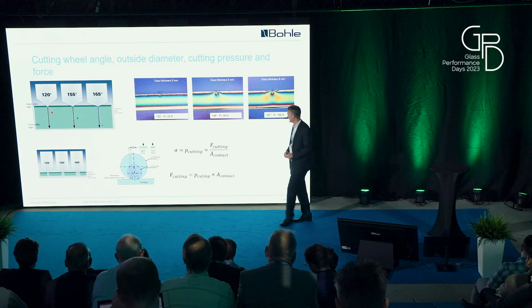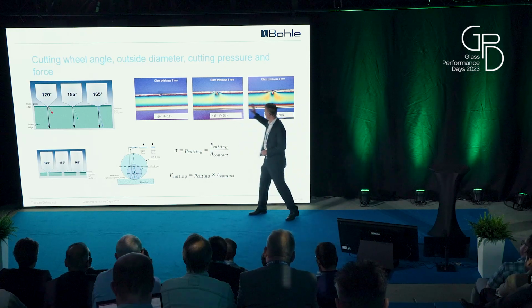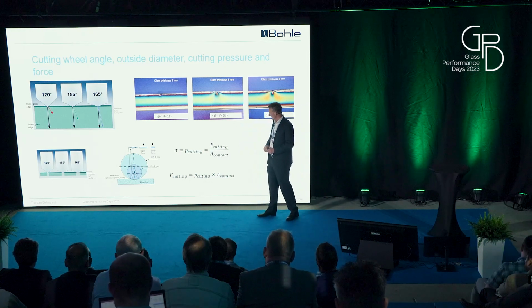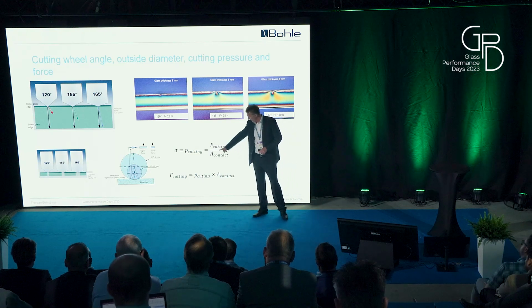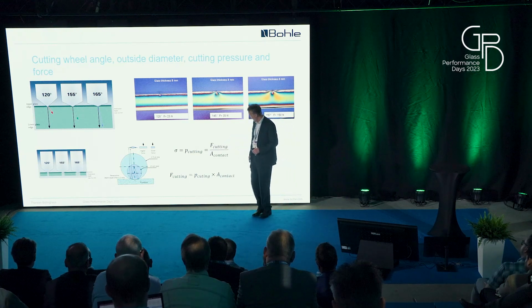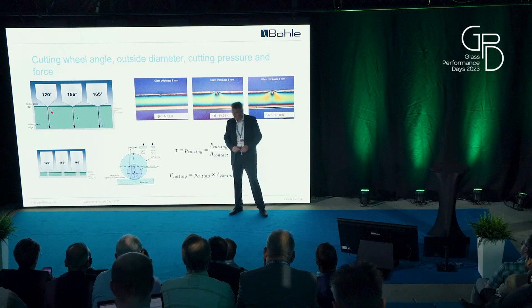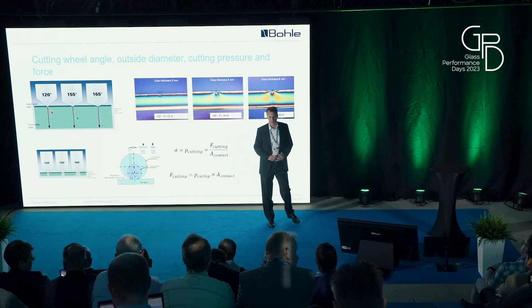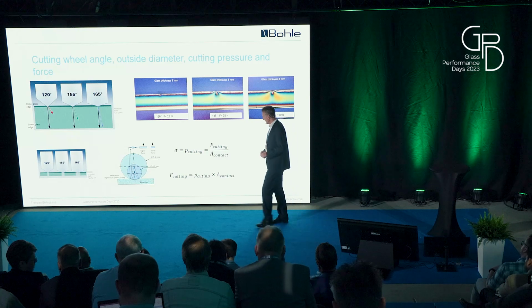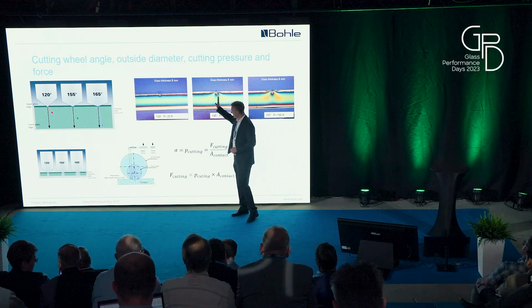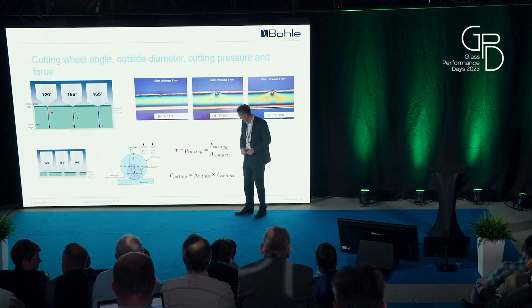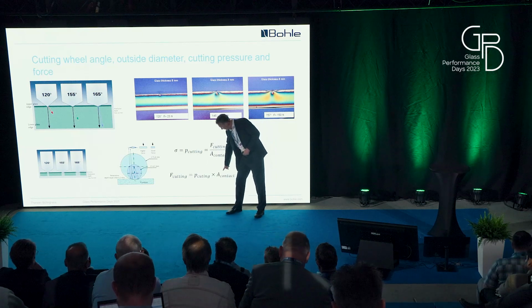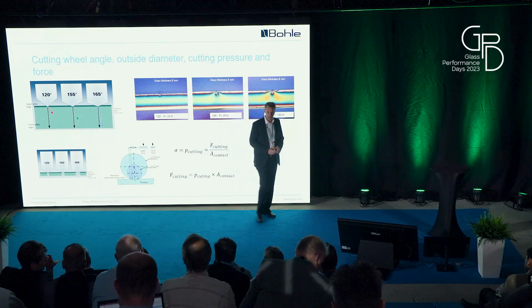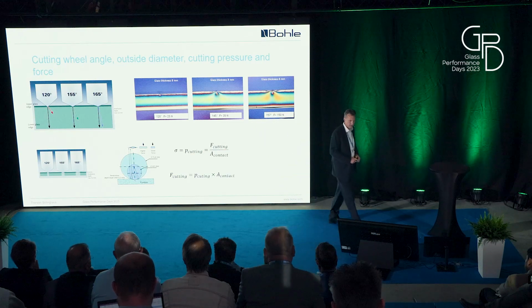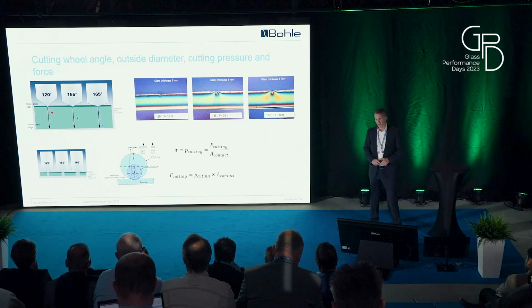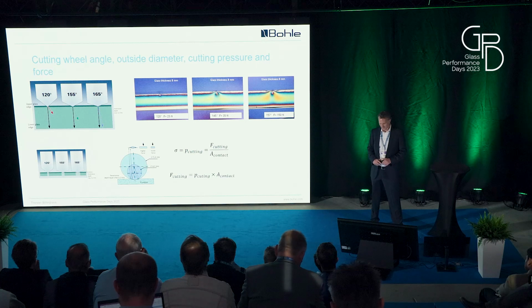The higher the force divided by the contact zone, the more you damage the glass surface. What we want, as said before, is to bring the tensions into the glass. So if you look at the equivalent formula, you say, I don't want to raise my cutting pressure too much because I don't want to destroy the glass surface, but I need a high cutting force to bring the tensions into the glass. If the pressure is limited, then you have to raise the contact area if you want to raise your cutting force. This is very important to understand, and on many production lines it is not so well understood.